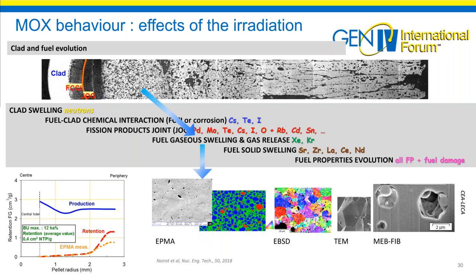So now, considering the fuel gaseous swelling on the curve representing the retention of fission gases in the fuel, it's noted that on the central part of the pellet, where we have the maximum temperature, all the gases are released, while in the peripheral part of the pellet, the lowest temperature reduces the gas diffusion. Under fast neutron conditions, we reach more than 80% of gas release for the whole pin.